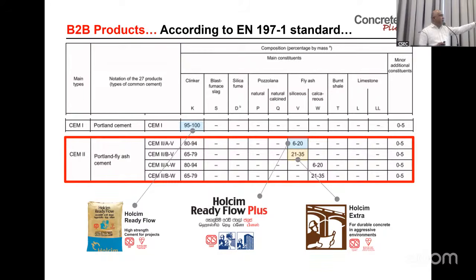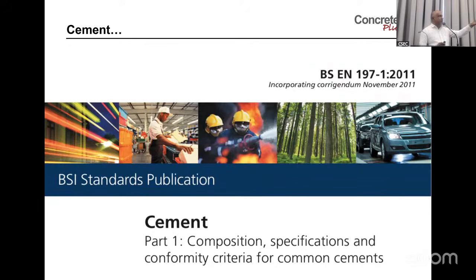This is from when I was in the cement industry. We had OPC and we had Holcim Extra, that is 21% fly ash, which is used for lotus tower. And in between, we found that we can make another cement with 6 to 20% fly ash, which is good for high-rise buildings. So this is the standard. If you want to refer, you can download it from Google, EN 197-1 2011. Later versions are there, but this is downloadable.